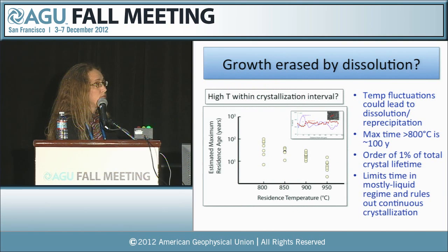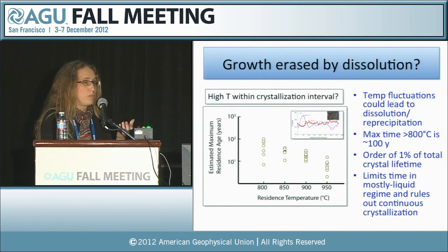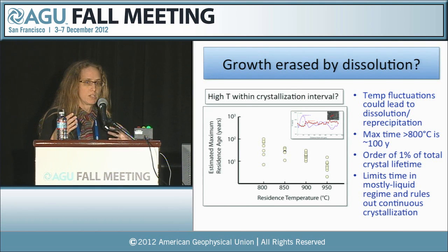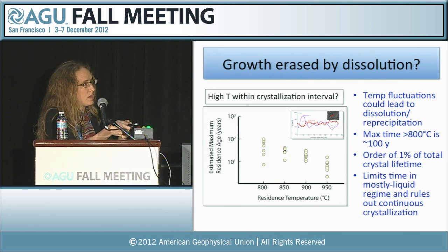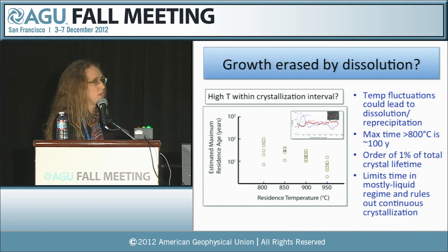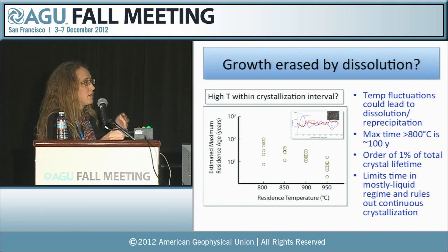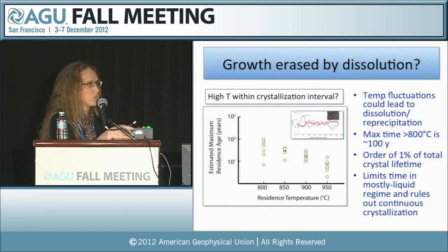So you can imagine a couple of scenarios in which dissolution might have been important. One of which would be if you have a magma reservoir which is sort of residing in the relatively high temperature interval, but still within the crystallization interval. Fluctuations within that could lead to a series of dissolution-reprecipitation events. But we can use the diffusion and the preservation of these disequilibrium strontium profiles to put a maximum amount of time that these crystals could have spent in that sort of high temperature window.